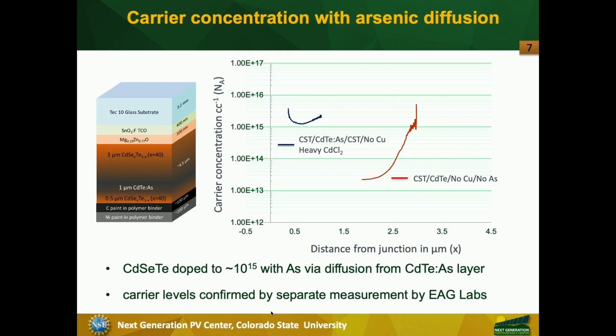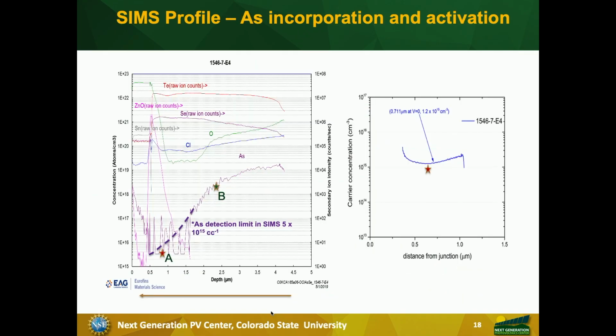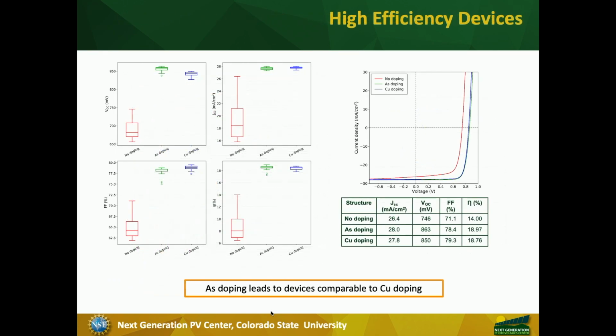We talked about copper doping. And recently we have started to look at arsenic doping as a replacement for copper. And here it shows that by doing certain process conditions, you can go from undoped material to an arsenic doped material. And here is an example of secondary ion mass spectroscopy, comparing it to the CV profile, looking at selenium and arsenic concentration versus how many holes are being produced. And we get about 20% activation here, which is quite high for this technology.